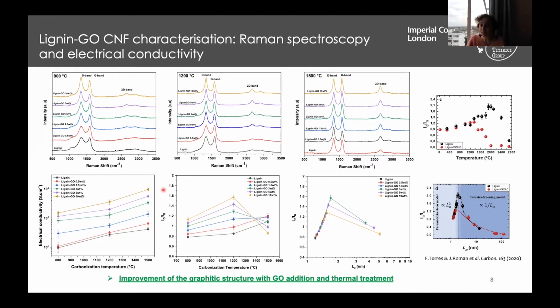Apart from this effect, we can see how the conductivity of our lignin fibers is increasing with the increase of graphene oxide content, and also carbonization temperature, as expected. And we can achieve conductivities of almost 10^2 Siemens centimeter^-1, which is quite a good improvement from the only lignin fibers.